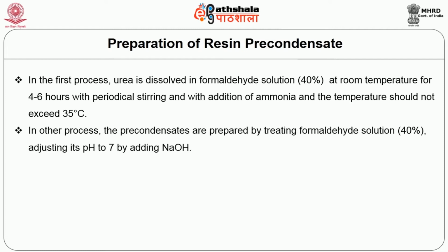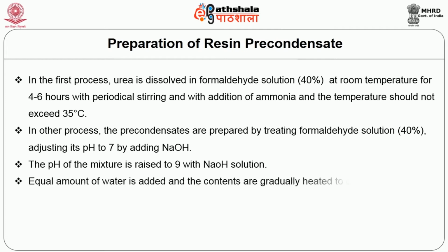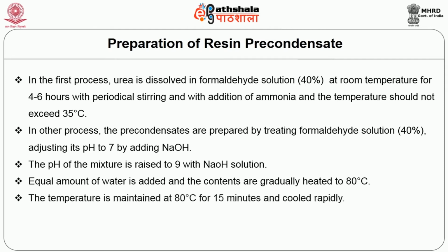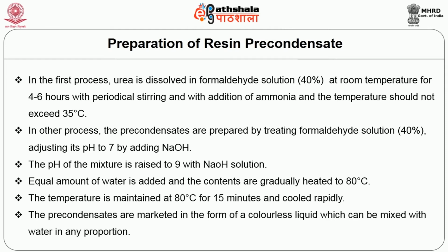In another process, the precondensates are prepared by treating formaldehyde solution, adjusting its pH to 7 by adding sodium hydroxide. The pH of the mixture is raised to 9 with sodium hydroxide solution. Equal amount of water is added and the contents are gradually heated to 80 degrees centigrade. The temperature is maintained at 80 degrees centigrade for 15 minutes and cooled rapidly. The precondensates are marketed in the form of a colorless liquid which can be mixed with water in any proportion.